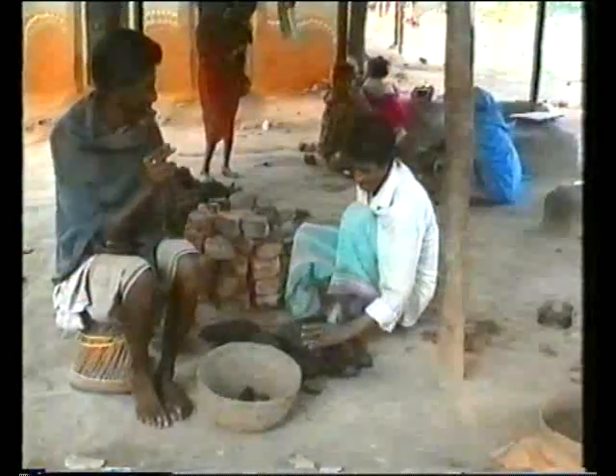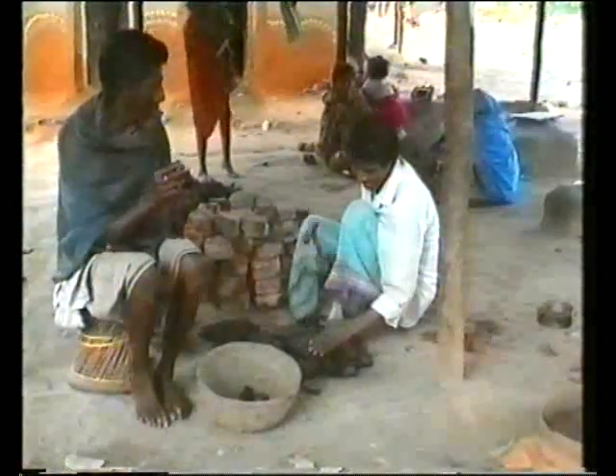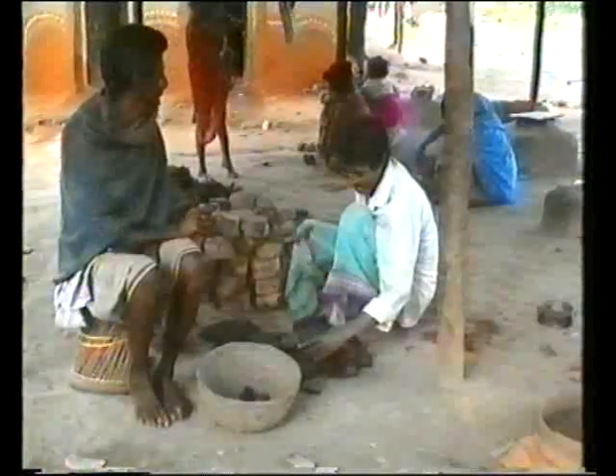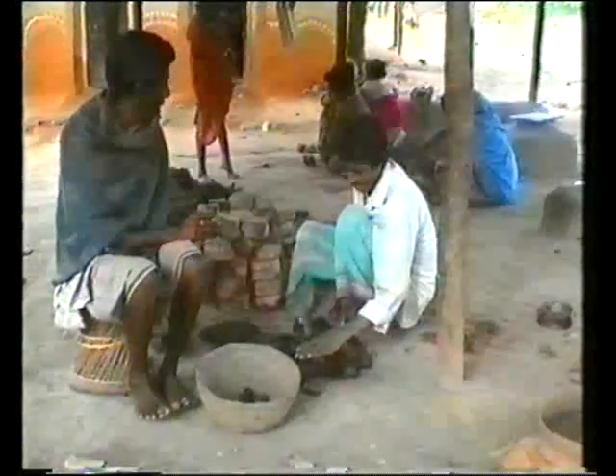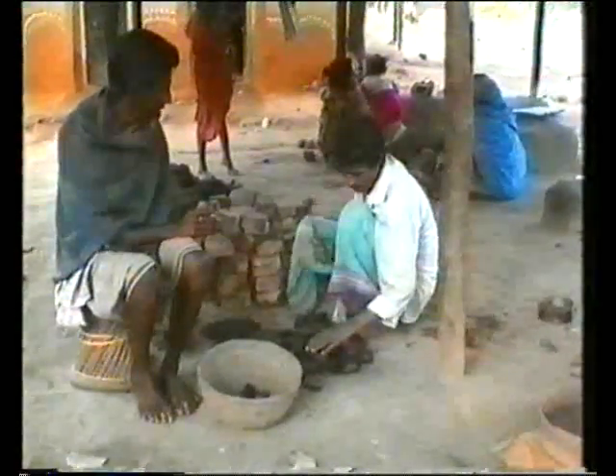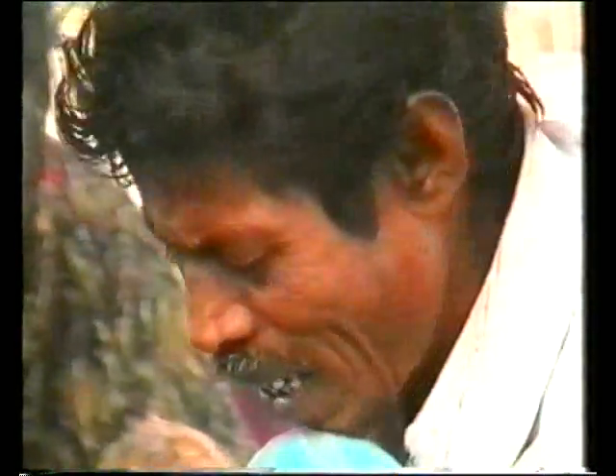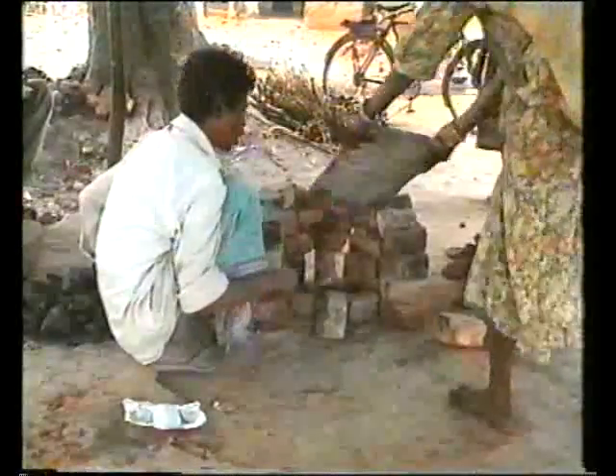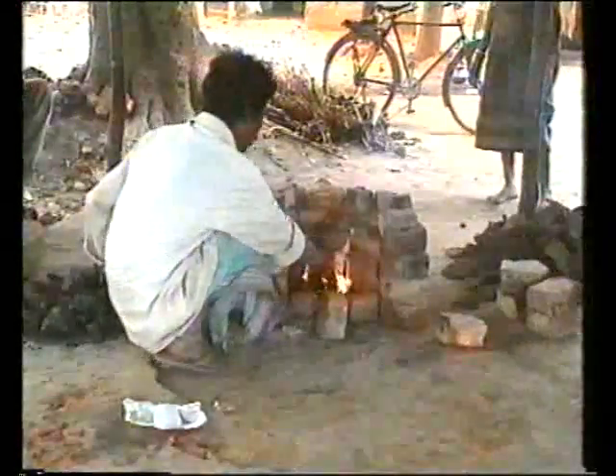Coke, a crude form of coal, is broken into usable-sized pieces. This will fuel the fire for the melting of the metal. The wax is melted out with a less intense fire made by burning cow dung. Melting the wax quickly can cause the mould to crack due to the heat quickly increasing the volume of the wax.